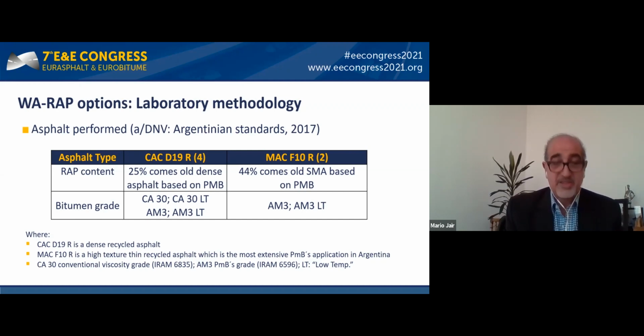Moving on to the warm RAP studied in the lab, these are the 6 warm RAP options designed for dense and thin mixtures. The dense mixes adding 25% of RAP from an all dense mix with PMB. The thin ones adding 44% of RAP from an all stone matrix asphalt, also with PMB. 4 types of binders were used. A conventional CA 30 bitumen, which is one viscosity grade according to the local standard in Argentina, and its low temperature version. And on the other hand, AM3, the most used PMB in Argentina, and again its low temperature grade.